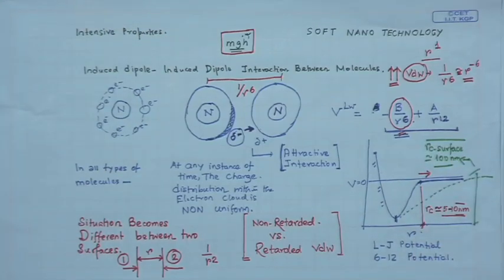Here is a quick take-home message: the nano scale is dominated by London dispersion forces, or the induced dipole–induced dipole type van der Waals forces, also called dispersion forces. This intermolecular induced dipole van der Waals force between two molecules stretches up to 10 nanometers with a scaling of 1 by r to the power 6. However, the same force is responsible for a rather longer-range interaction up to 100 nanometers between two surfaces, where the scaling changes to 1 by r squared.